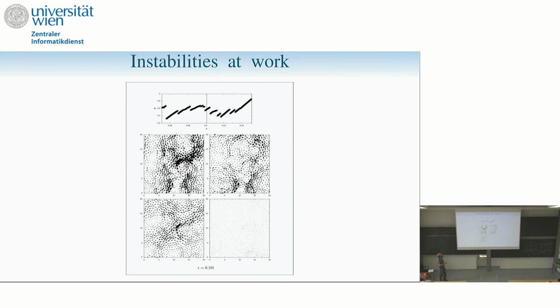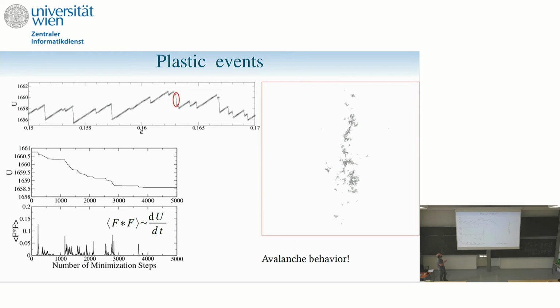What you see is that, first of all, if you look at energy versus the number of minimization steps, the minimization of energy is very intermittent. And if you look at F, the square force is the equivalent of the rate of change. Zoom in on this red. Exactly. So I just take this drop, and I look at what happens during the minimization.